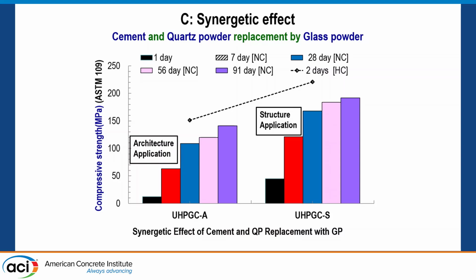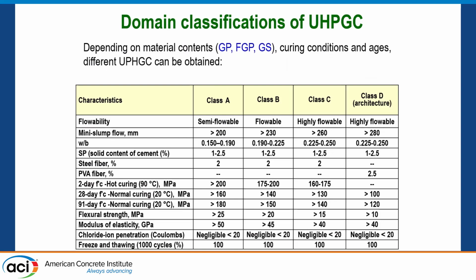So we compared here the compressive strength also with 2 days of the hot curing. I didn't say that, but in all the slides we did it on hot curing also to compare at 2 days. So then here you have classification of different types. So you go from semi-flowable to flowable to highly flowable, and also if you go to more definition of your surface in the architectural design, you can go to even more flowable. So we have different situations where you can use it. Of course, you have to pay the price for flowability or for compressive strength, depending on your goal.